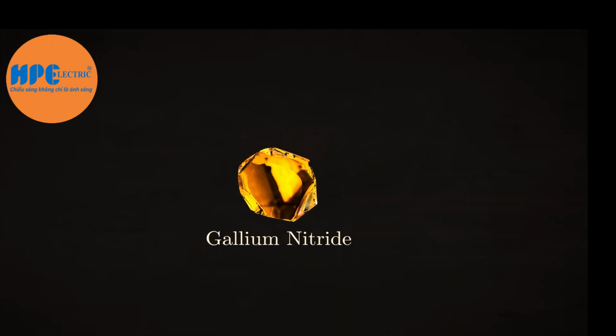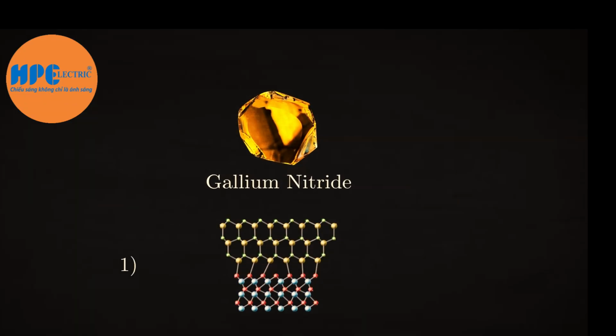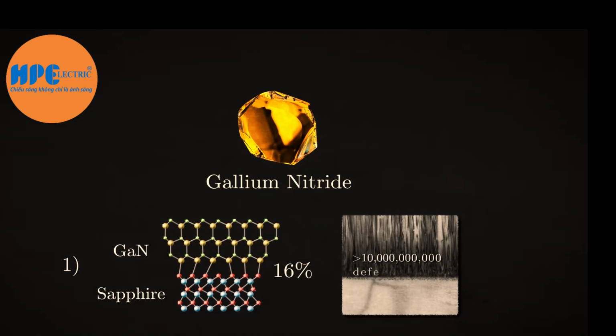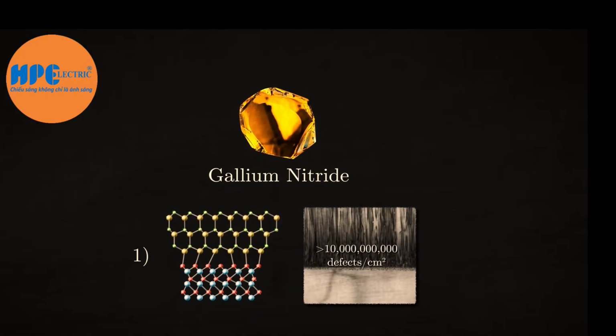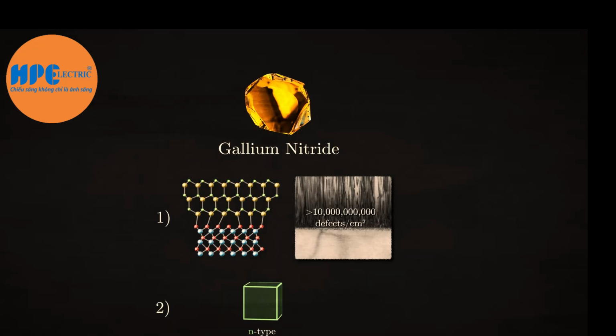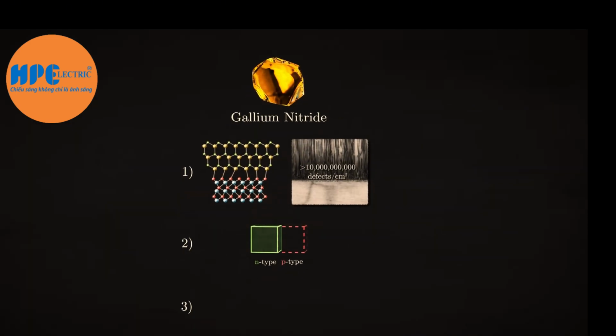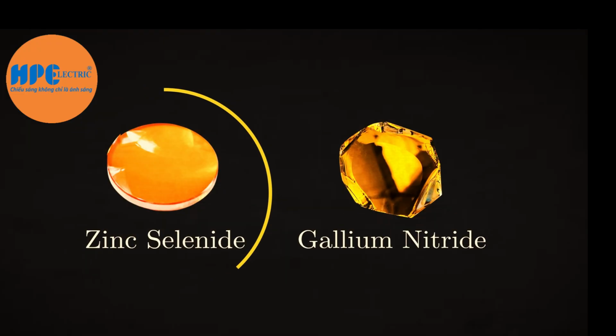In contrast, gallium nitride had been abandoned by almost everybody for 3 reasons. First, it was much harder to make a high-quality crystal. The best substrate for growing gallium nitride was sapphire, but its lattice mismatch was 16%. This resulted in higher defects, over 10 billion per square centimeter. The second problem was that, like zinc selenide, scientists had only ever created N-type gallium nitride using silicon. P-type was elusive. And third, to be commercially viable, a blue LED would have to have a total light output power of at least 1,000 microwatts. That's 2 orders of magnitude more than any prototype had ever achieved. So between the 2 candidates, almost all researchers were focused on zinc selenide.